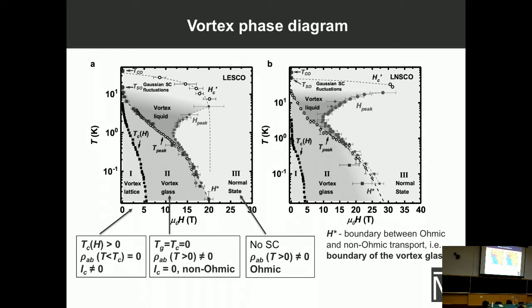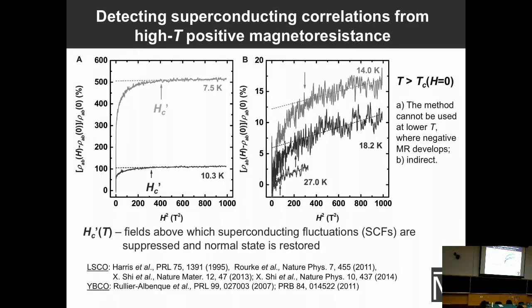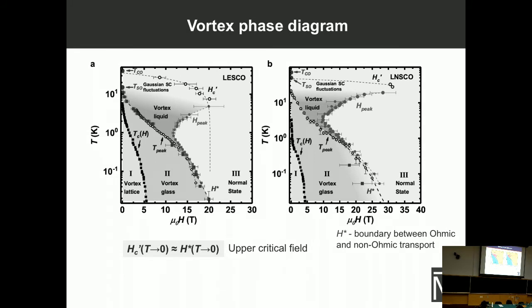So we also have these points here, blue points. They're determined at high temperatures, as you can see, from the region where magnetoresistance is still just positive. And this is just using the same method that's been applied before. Basically what people find is that at high temperatures, magnetoresistance is positive, and at high enough fields it goes as H squared, which is what you expect in a metal. So you can identify this field where it starts to deviate from that behavior as the onset of superconducting fluctuations. So these are these blue points, and there are just a couple here.